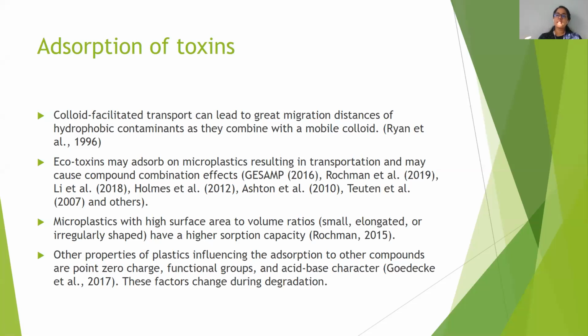So we know that these microspheres adsorb contaminants, and it moves them. And then further studies on microplastics itself found that ecotoxins also may adsorb to the microplastic, resulting in transportation. That is specifically in the marine and surface open freshwater environments. Microplastics with a higher surface area to volume ratio have a higher adsorption capacity.